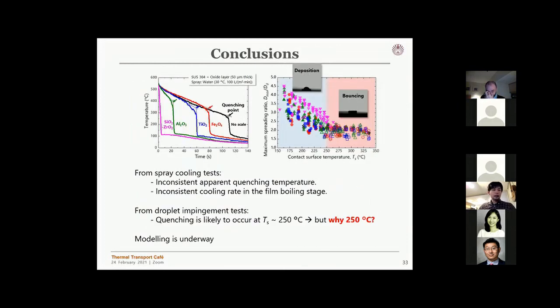Okay, so I've talked too much today, but these are the basic conclusions of my talk. I've shown you two different experiments. From a spray cooling test, I pointed out that there's a huge impact by the oxide layer on quenching temperature, so we have inconsistent apparent quenching temperatures. Also, the cooling rates are different for different oxide layers.